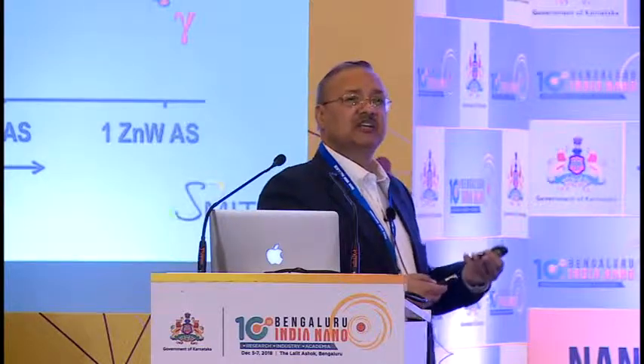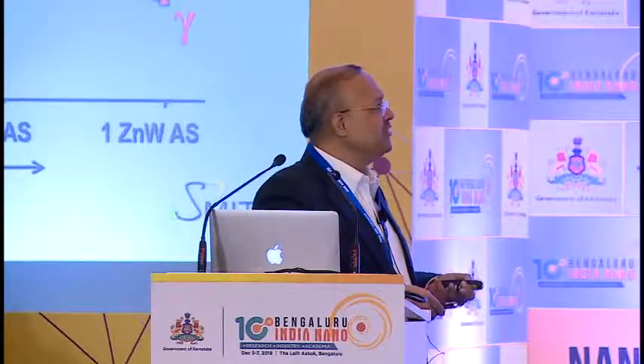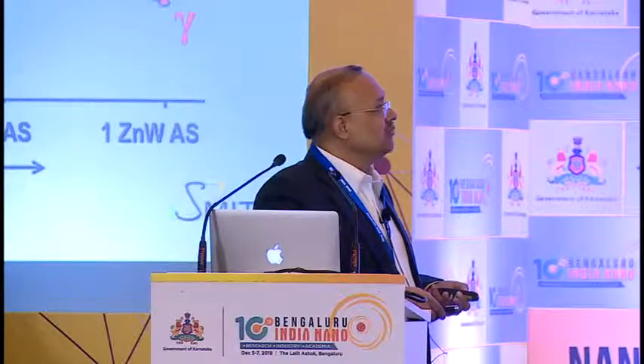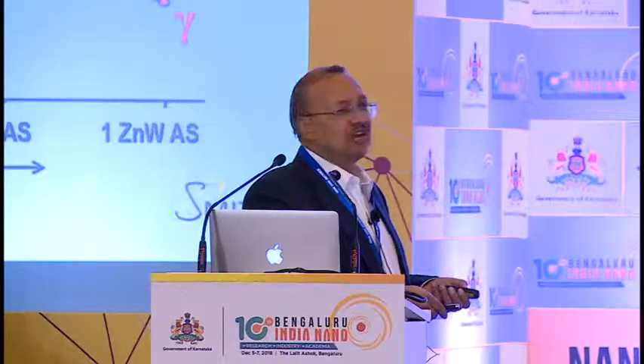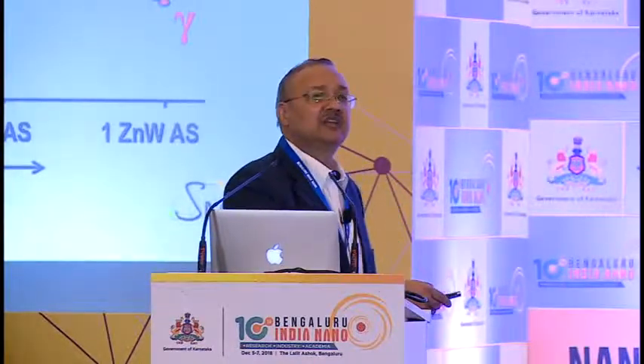And we saw that the material characteristic, the crystal structure of the fiber itself, changed dramatically. Where we had a gamma phase more in nylon and alpha less, if you add a particle, even gamma becomes more. But when you keep on increasing the dimensions of these nanomaterials, the whole story reverses. And it reverses not so much at the rods, but at wires it is absolutely a different story. And when you have an alpha structure of nylon created, the strength just shoots up like anything.